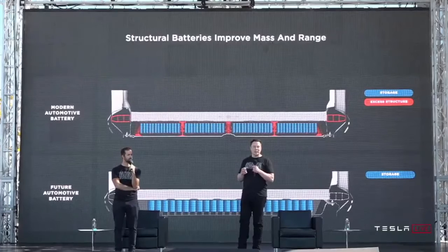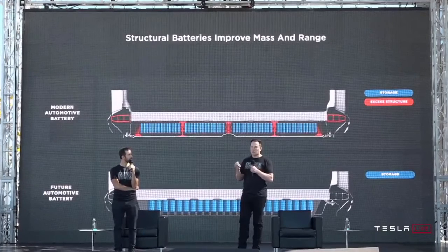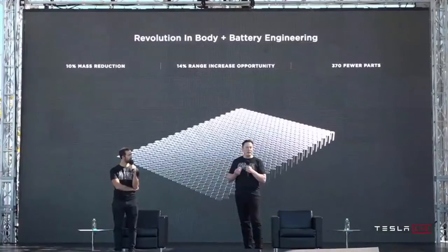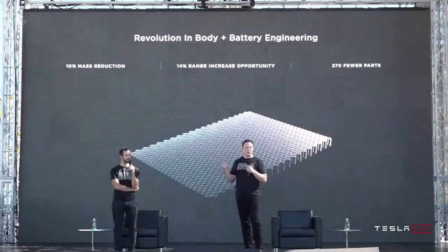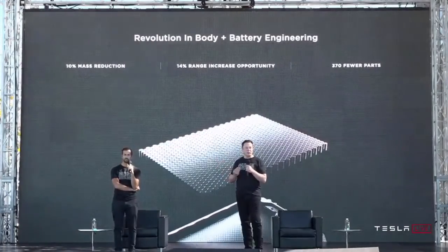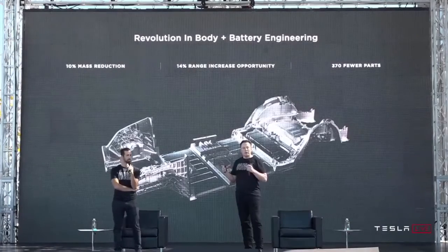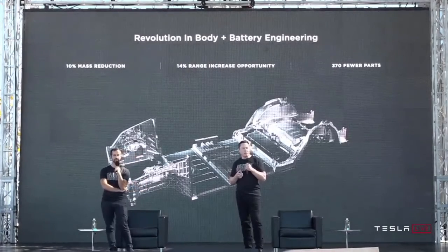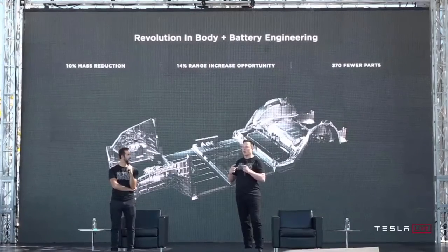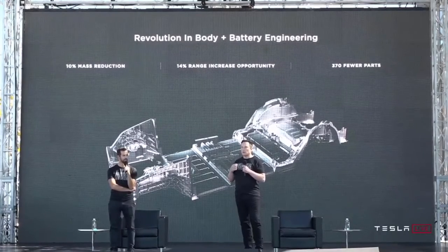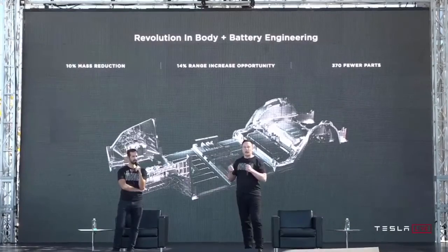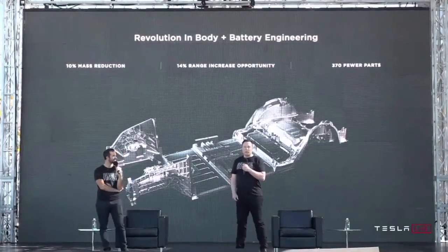The volumetric efficiency of the structural pack is much better than a non-structural pack, and we actually bring the cells closer to the center, and because they're closer to the center, it reduces the probability of a side impact potentially contacting the cells, because any kind of side impact has to go further in order to reach the cells. If you can bring things closer to the center, you reduce the polar moment of inertia, and that means the car maneuvers better. It just feels better. You don't know why, but it just feels more agile. It's really cool. This is really major.